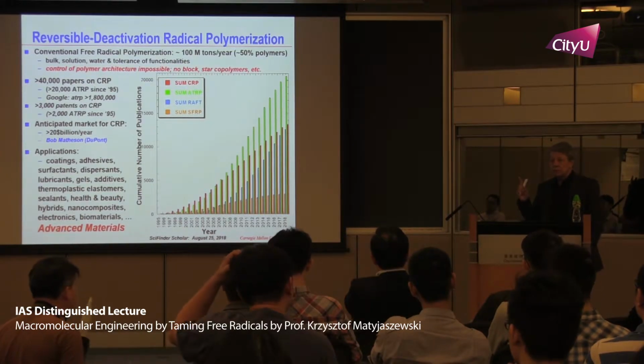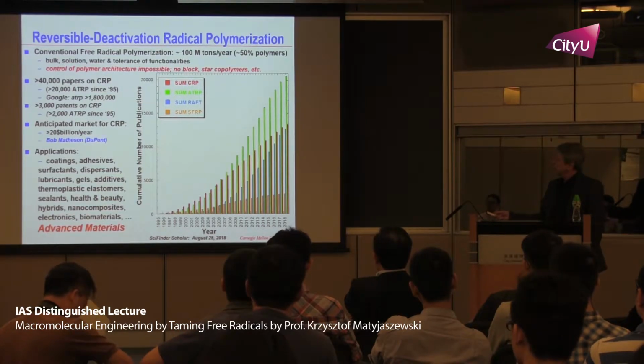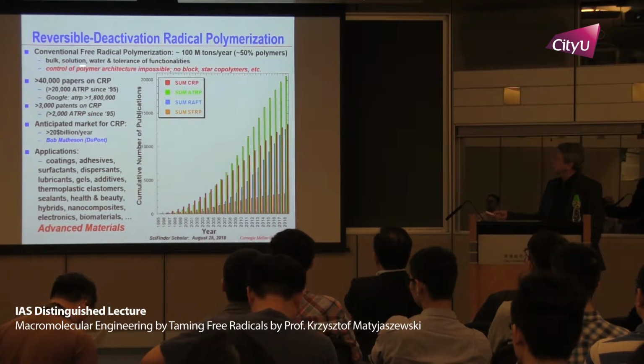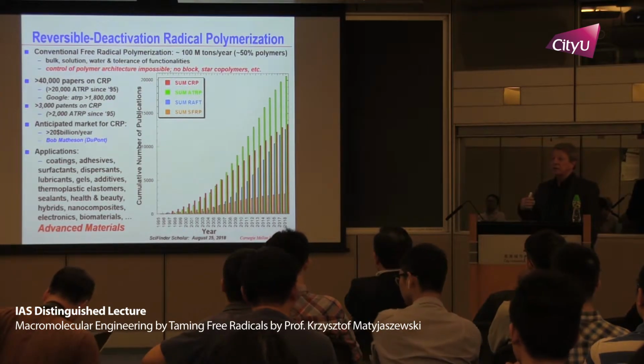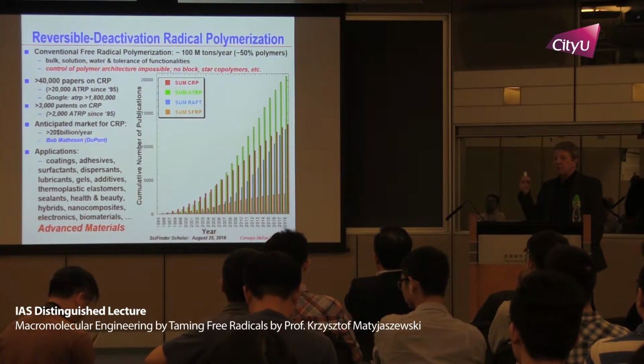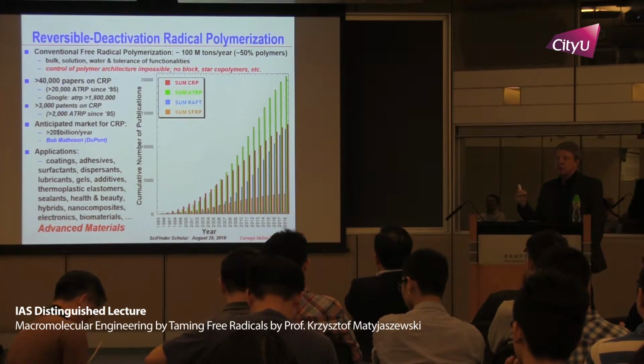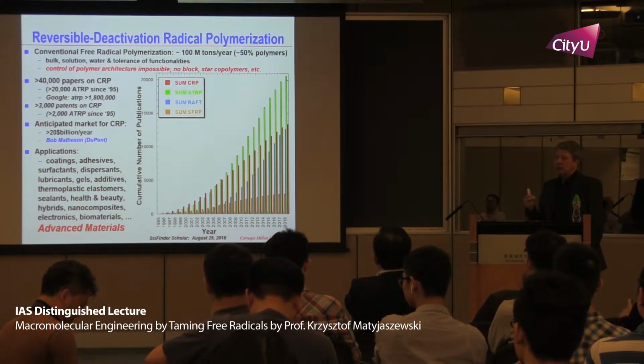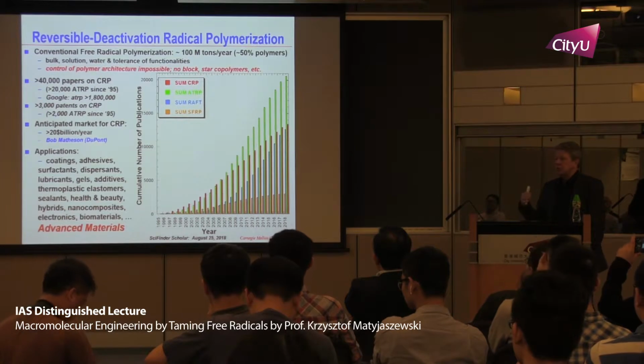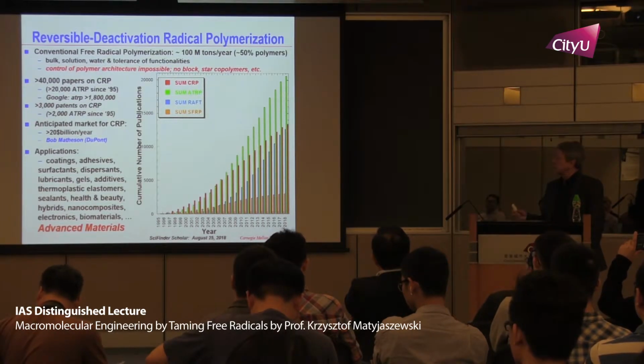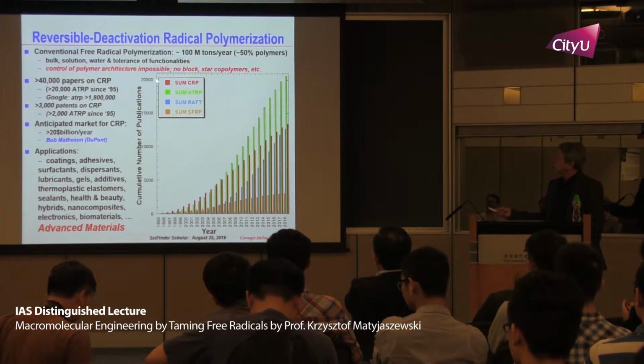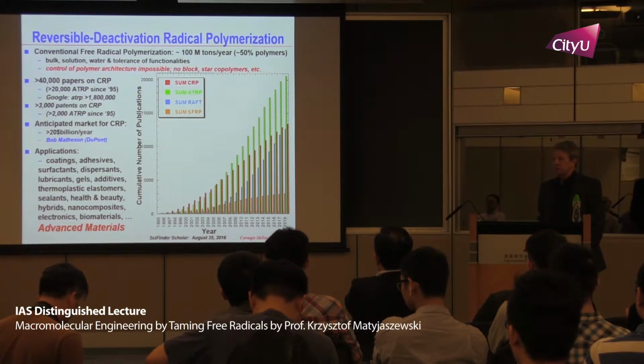However, there is a problem with this process. Although it can be run in bulk, in solution, in water, in very large tolerance to many functionalities, the life of propagating chain is only 1 second. So 1 second is too short to make block of polymers, sophisticated structures, so you cannot control polymeric architecture. No block of polymers, star polymers, and so on.